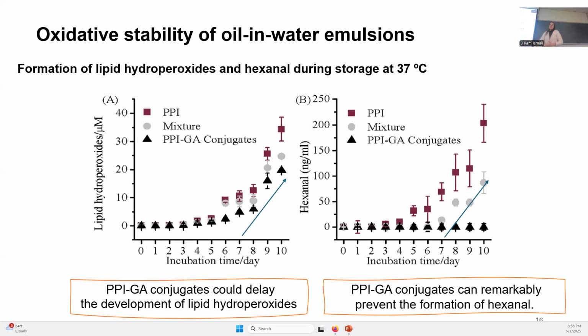And then finally, the oxidative stability. What you're seeing here is the first graph is the formation of lipid hydroperoxides, which are the first primary oxidation products. And the second one is the formation of hexanal, which is a secondary oxidation product. So for the first one, the formation of lipid hydroperoxides, we see that the formation increases after 7 days of storage, and the conjugates have a delay in the formation of these hydroperoxides.